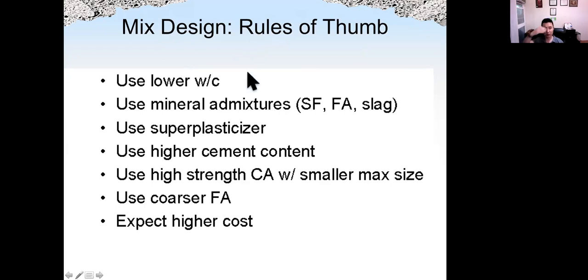So for high strength concrete or high performance concrete, the rule of thumb is to use a lower water cement ratio. If possible, use fly ash, silica fume, and slag. Use superplasticizer if workability is a concern, and we should use higher cement content to compensate for the lower workability. Reduce the size of aggregate, use high strength coarse aggregate, and use a larger size of sand or fine aggregate. But the cost will be higher because of these materials.